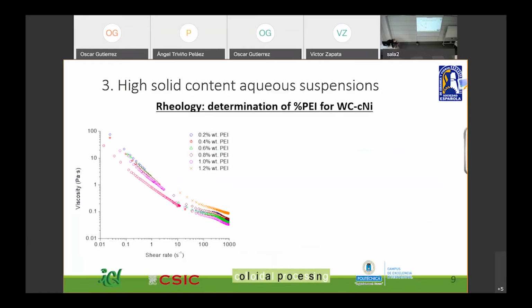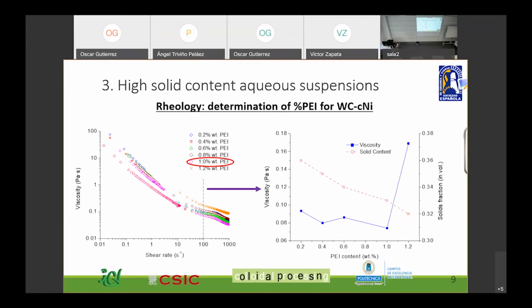So after that, the first thing we did was carry out some rheological tests to determine the optimal amount of dispersant we are going to add to our suspensions. In our case, we decided to use polyethylenimine, or just PEI, which is an organic polyelectrolyte, to stabilize our particles in suspension. After this test, we added different proportions of PEI, and as we can appreciate here, there is an optimal amount of PEI, which is 1% in weight.